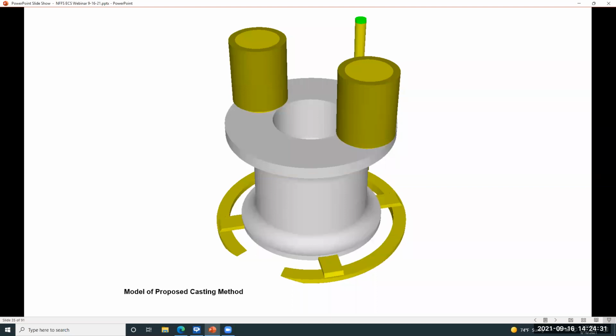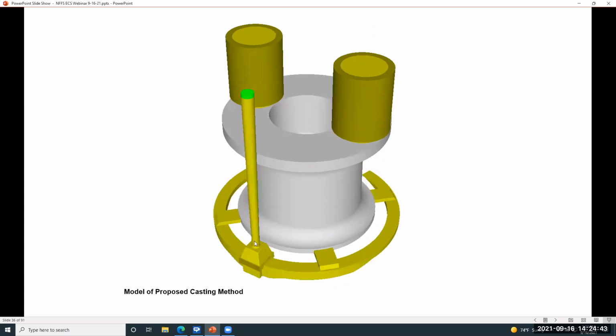This shows what the gating and risering system looks like based on those calculations. We can see that we have top risers here with insulating sleeves. We can see that we have a round tapered sprue. We have a double runner. Incidentally, when we look at the runner, we can see that this is what's known as a step-down runner, which allows equal flow through each gate. You can see after the first gate, the thickness of the runner is reduced. That's so that we maintain a constant cross-sectional area and a constant flow rate through each individual piece of the gating system.